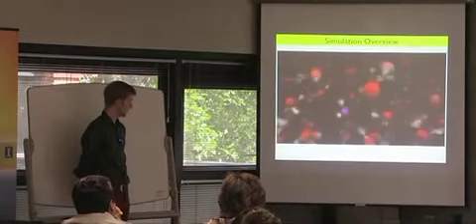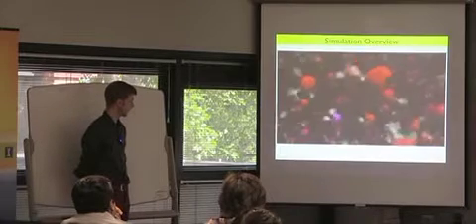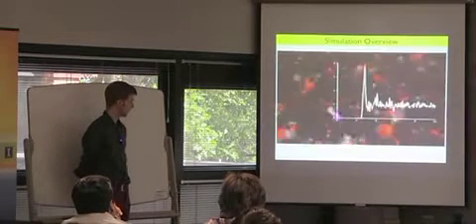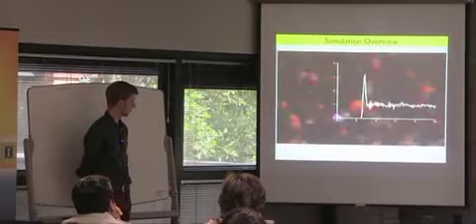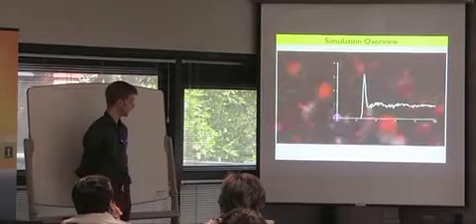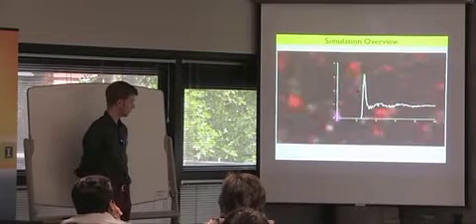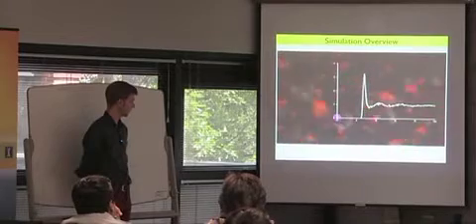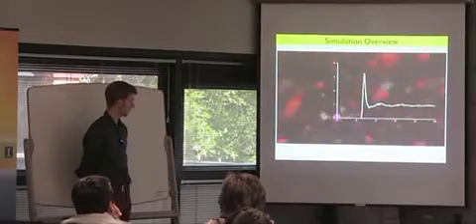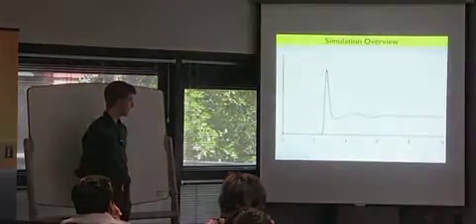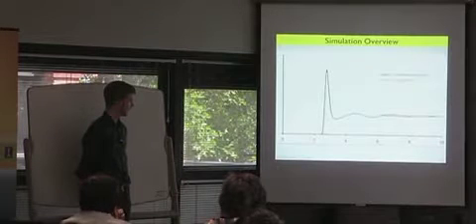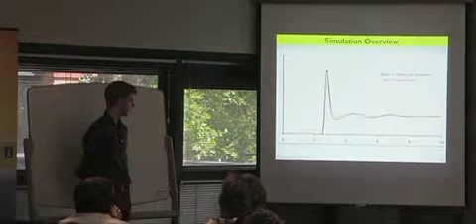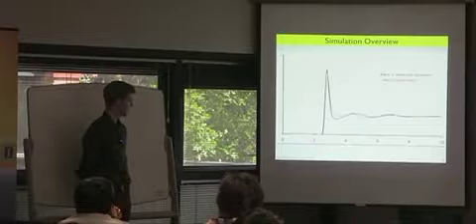So if we plot the average probability of finding an oxygen in a unit volume with distance out from a specific water molecule, we get what we would call a radial distribution function. Now it turns out these structural functions can actually be measured directly via experimental methods such as neutron scattering. As you can see, these very simple methods do an okay job of modelling the structure of water.